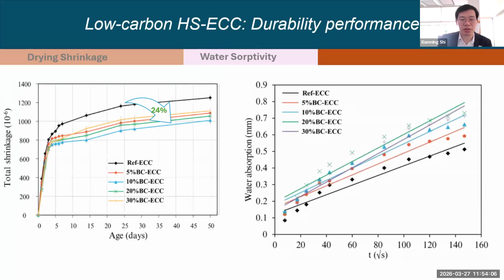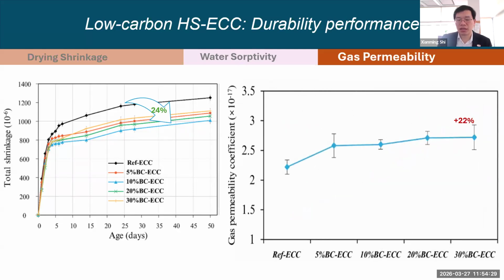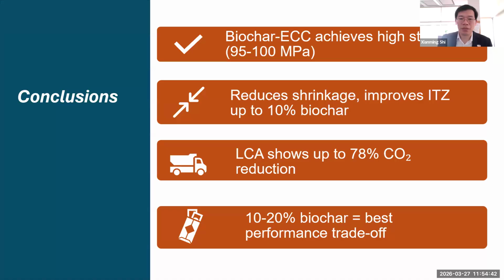And what about drying shrinkage? Okay, here we also see 24% lower drying shrinkage. That's good. Water absorptivity, again, that's the bad news: a 48% increase. So unless we use some sort of admixture to mitigate that, or depending on the service environment, whether it's a concern or not. Gas permeability, again, is an indicator of physical microstructure, how dense they are. Here we're seeing a 22% increase, which means they're not as dense as the reference. Again, that could be a concern.